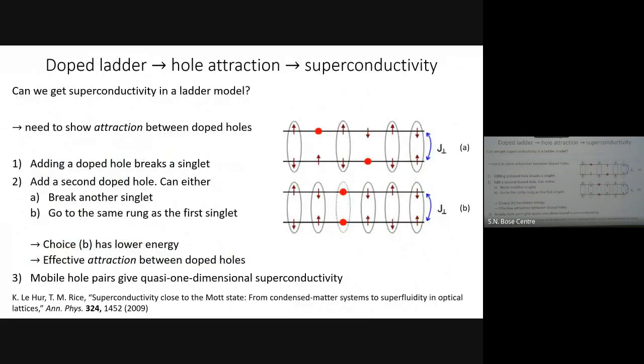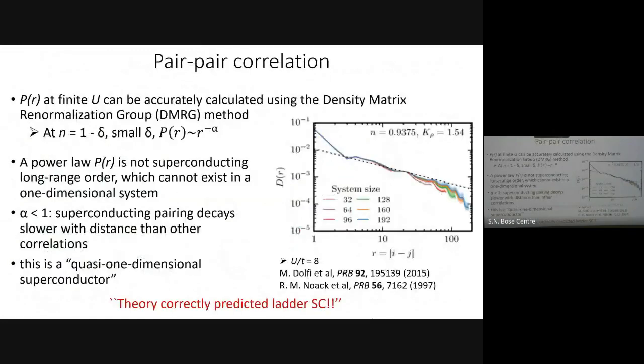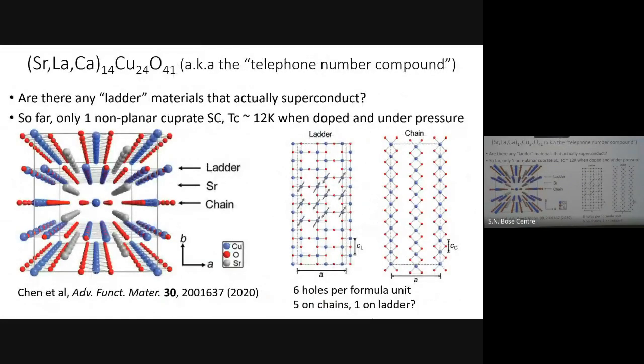It turns out that actually, I don't know if I have a slide for the calculations. Yes. Okay. So in parallel, there is a real material of this composition. When it starts with strontium 14, that's a semiconductor. You replace some of the strontium with calcium, same valency, but size is different. If you go to calcium 11, it actually becomes a superconductor. What's the structure? These are layered structures. This is important. Now it becomes serious, even though it is fast-paced. So these are chains that look like this.